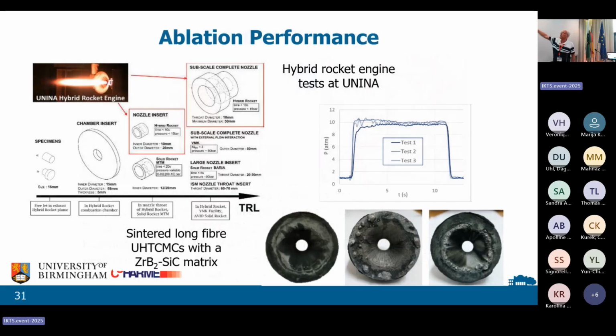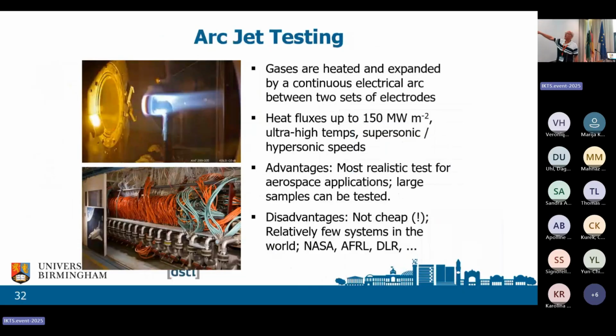Then you've got the rocket test. These are done at UNINA, the University of Naples. And you can see the sorts of damage that the nozzles took. These are baby nozzles, about this size, nothing like the full-size nozzle. And then you've got the arc jet testing, which is done at DLR. It's a wonderful test. It's the closest to real life. 150 megawatts. It's 10 times the heat flux of an oxyacetylene torch. It's the most realistic. It is not cheap. Tens of thousands of euros per run.